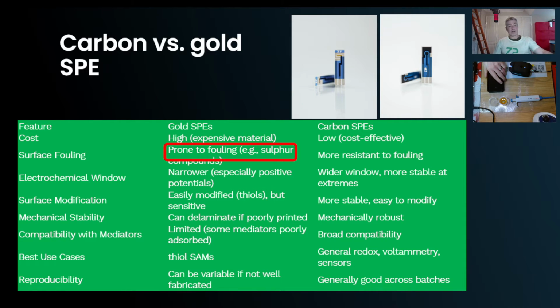If you go anywhere where they've got gold objects, one of the things that people do with gold is they polish it, and over time it gets dulled, and it's basically absorbing materials from the atmosphere. I've realized now that carbon is actually quite resistant to fouling. It's not absorbing thiol molecules from the atmosphere and tarnishing. Just FYI, when we are using carbon or gold electrodes in building biosensors, we do use an activation step as part of our manufacturing. So we do actually clean them. We do clean both.